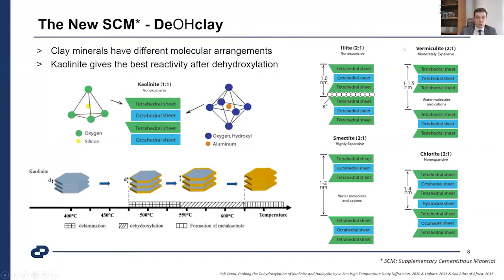composition. That 1-to-1 composition is based on an oxygen silicon tetrahedral sheet and a single octahedral sheet, with oxygen hydroxyl groups and alumina. And with the thermal process, as you can see in the bottom part for kaolinite, it starts after 500, 550 degrees with delamination, and then dehydroxylation starts, and after that the formation of metakaolinite. Metakaolinite is a known product with high purity of kaolinite. Many industries also use it.